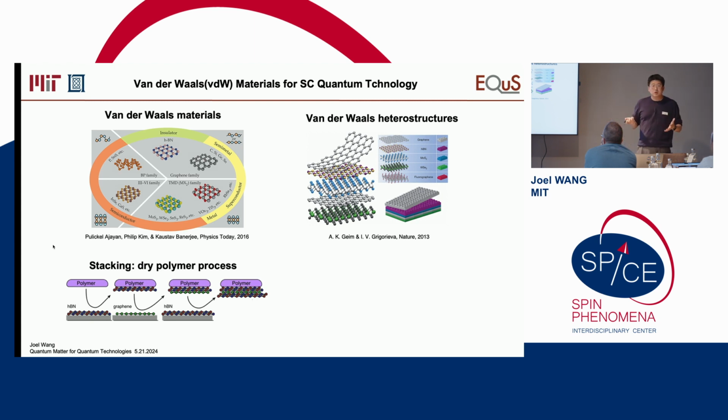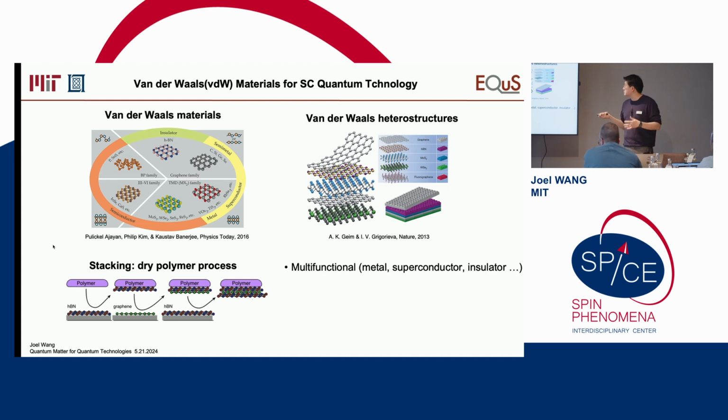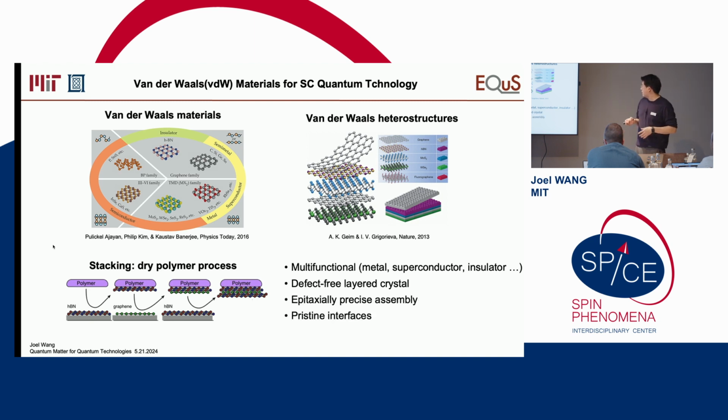We're interested in this material in this context in particular because this family of materials is multifunctional. You get all kinds of flavors of material that can basically build a whole device. Ideally, it's a defect-free layered crystal, so it's good for coherence. It can be epitaxially assembled, so that you have pristine interfaces. And also, something that comes in handy is that it's compatible with the circuit QED architecture, which is 2D.